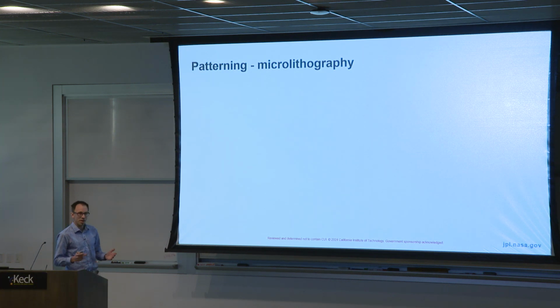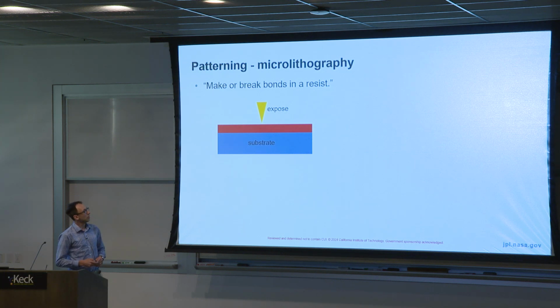Patterning, or micro or nano lithography. Essentially what we're talking about now is making or breaking bonds in a resist, and a resist is a liquid that's either photo or e-beam sensitive most of the time. You dispense it onto your wafer, and then you spin your wafer really quickly, typically at a few thousand RPMs, and the resist reaches a hydrostatic equilibrium on the surface, which is a way to create highly uniform coatings onto a wafer.